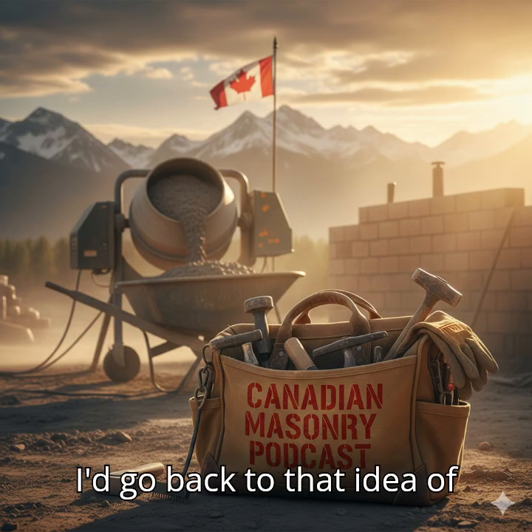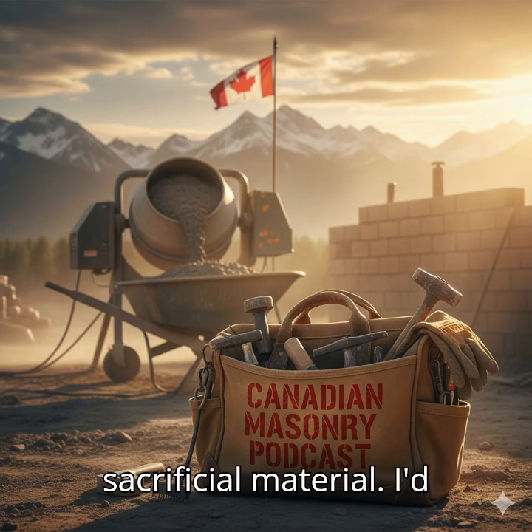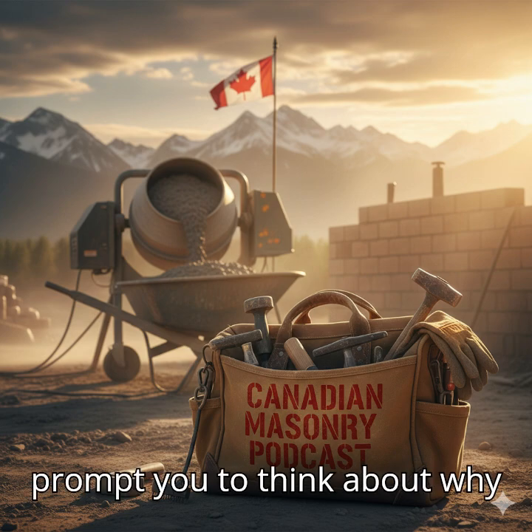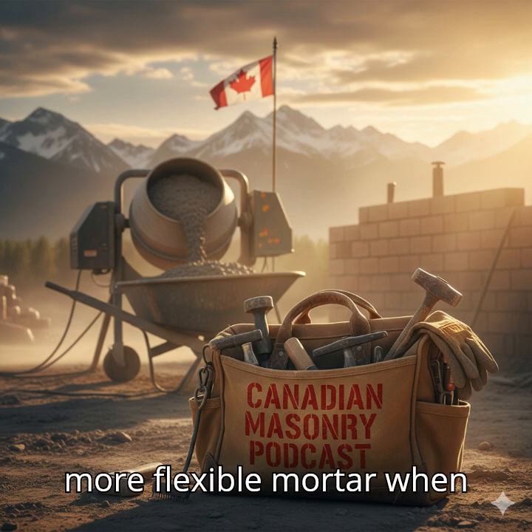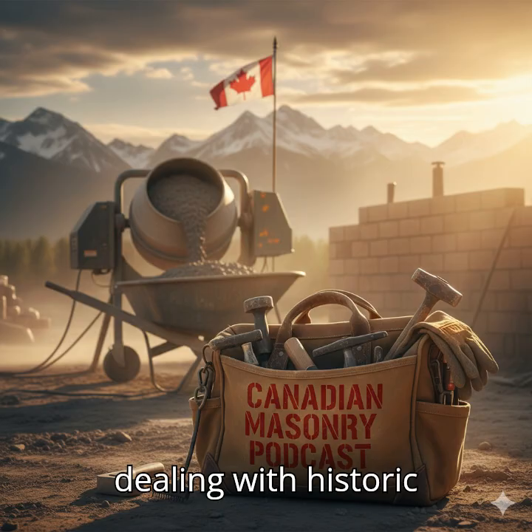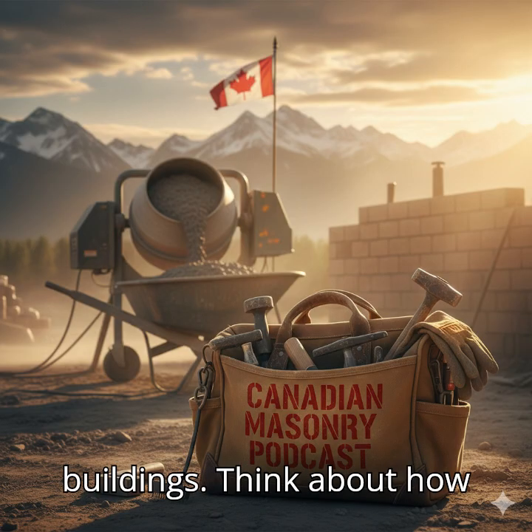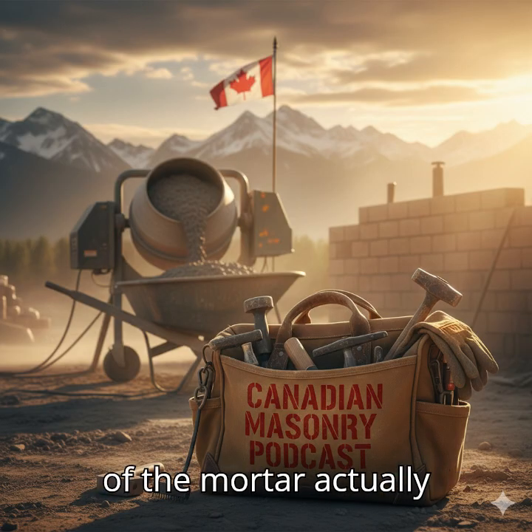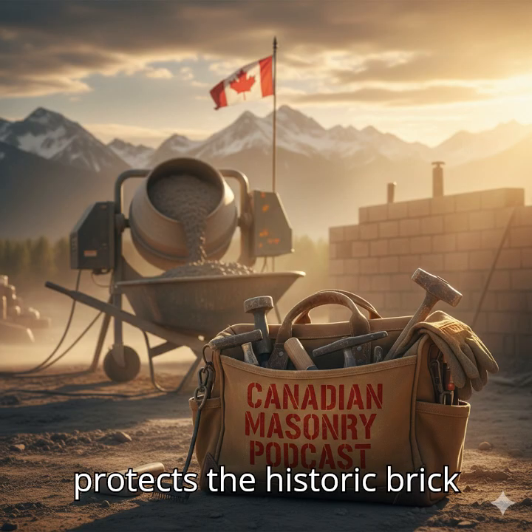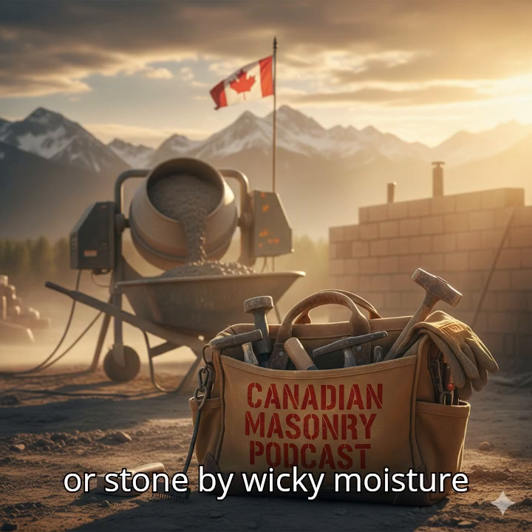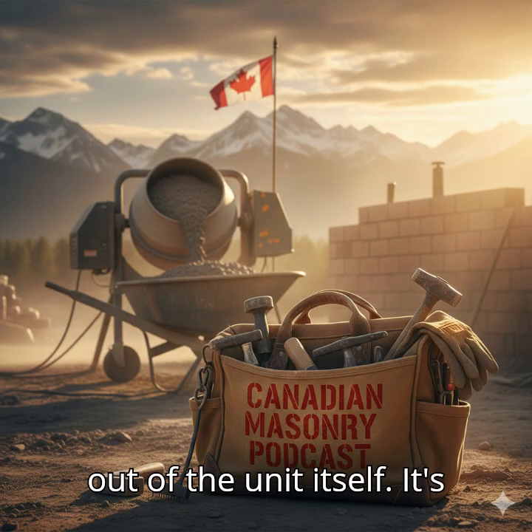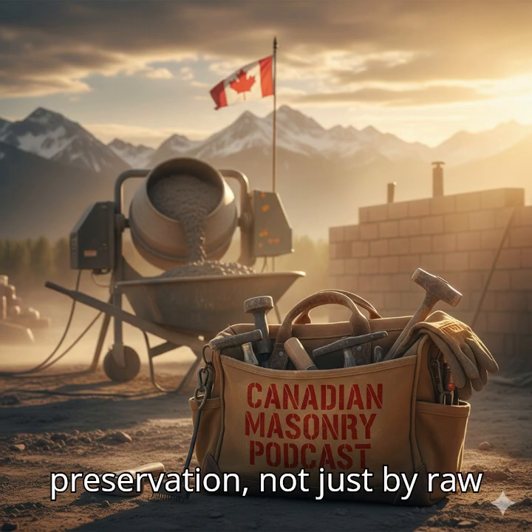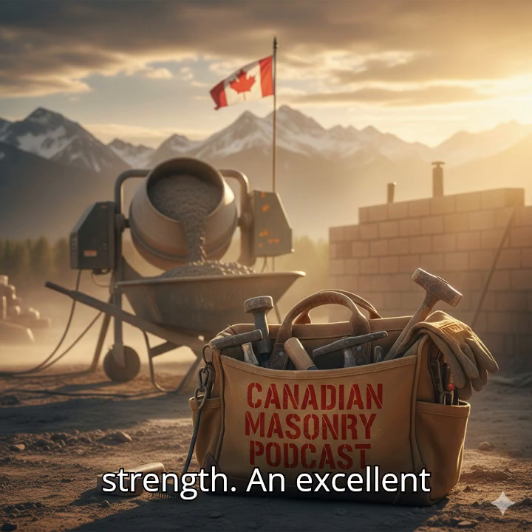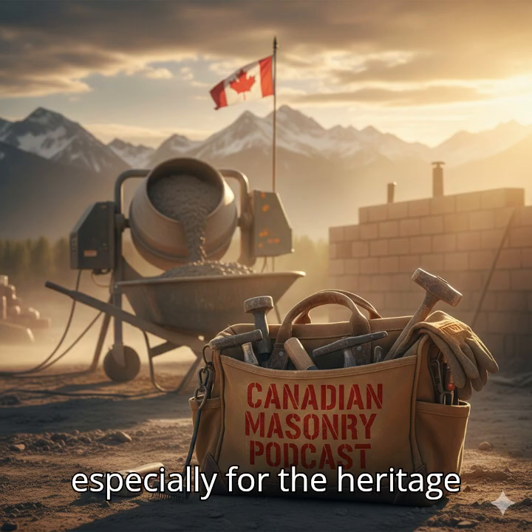I'd go back to that idea of type O mortar being a sacrificial material. I'd prompt you to think about why it's better to have a weaker, more flexible mortar when dealing with historic buildings. Think about how the relative absorption rate of the mortar actually protects the historic brick or stone by wicking moisture out of the unit itself. It's a choice driven by preservation, not just by raw strength. An excellent thought to consider, especially for the heritage side of our trade.